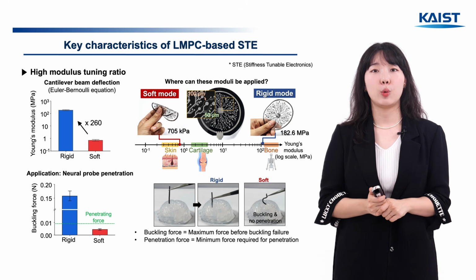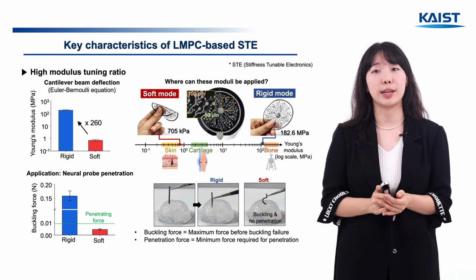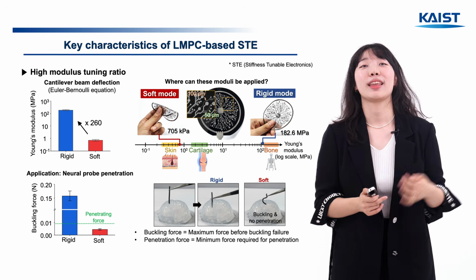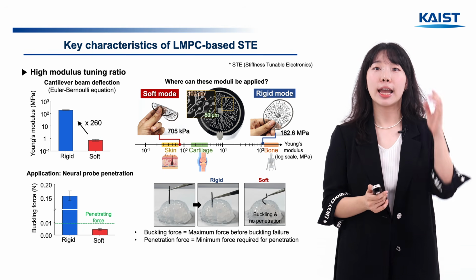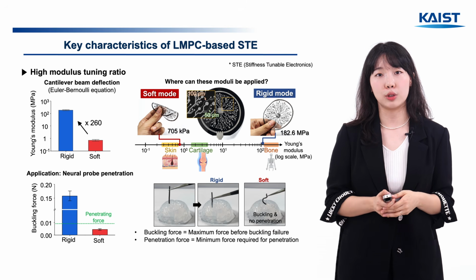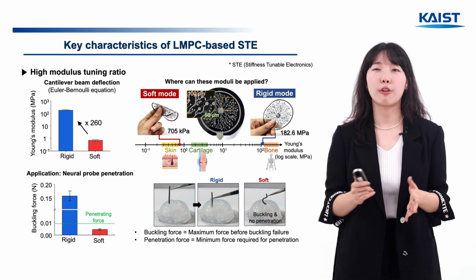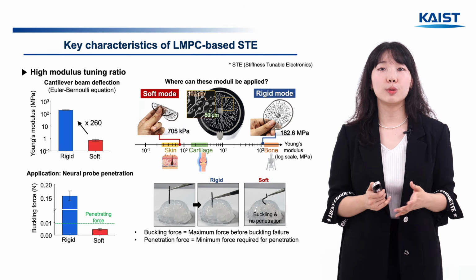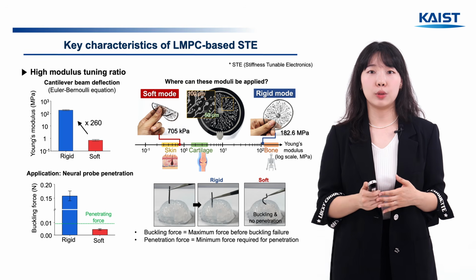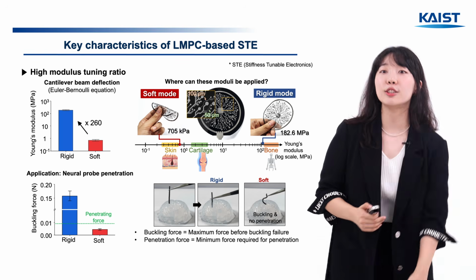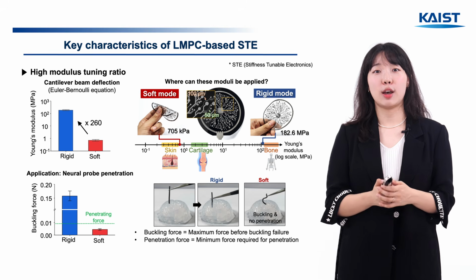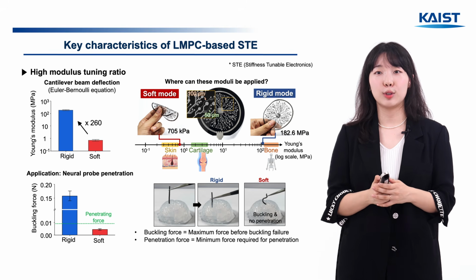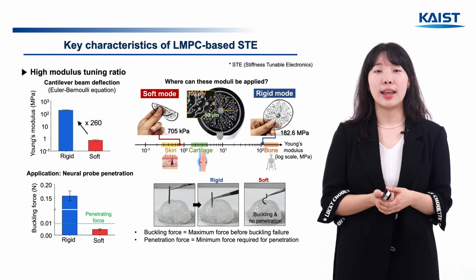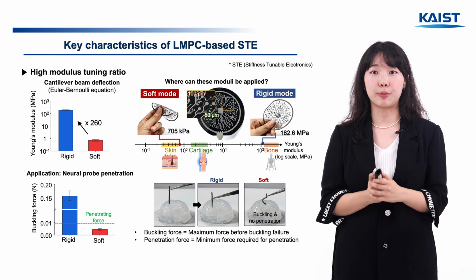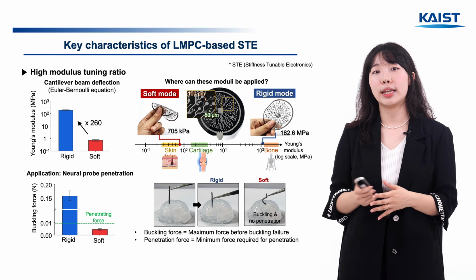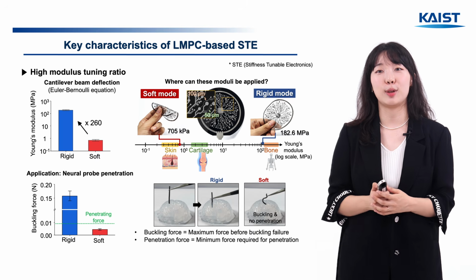With the LMPC ink, we achieved high-resolution printing down to 50 micrometers, about the size of a hair, and we measured the bending stiffness of the device and used the Euler equation to calculate the Young's modulus, which gave a stiffness tuning ratio of around 260-fold. Soft mode was similar to skin, while rigid mode fell between the Young's modulus of cartilage and bone. To make use of these two modes, we developed a stiffness-tunable neural probe as an application, and in its rigid mode, the probe can penetrate the brain without buckling, and in its soft mode, it cannot penetrate but instead causes less damage to the tissue.